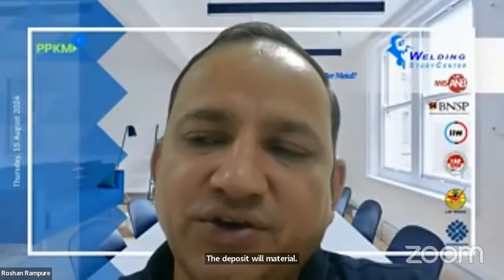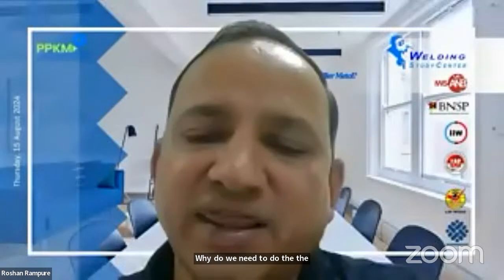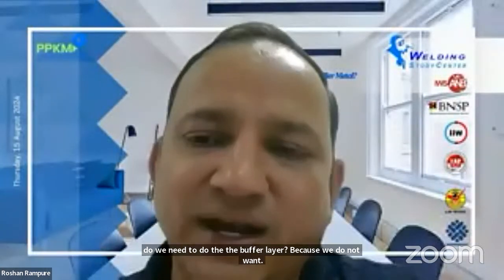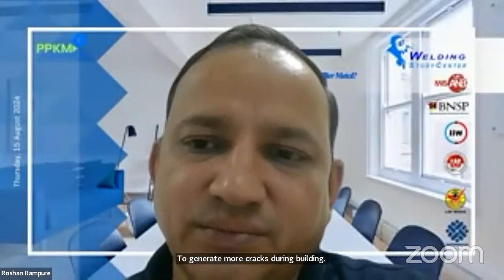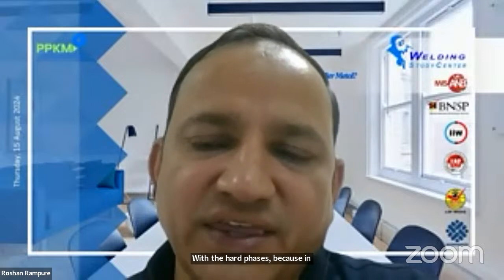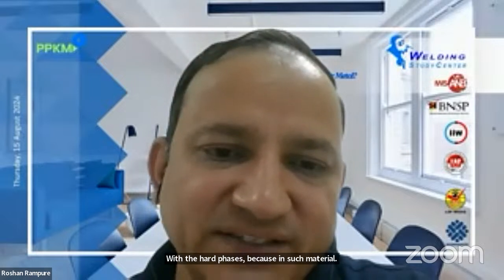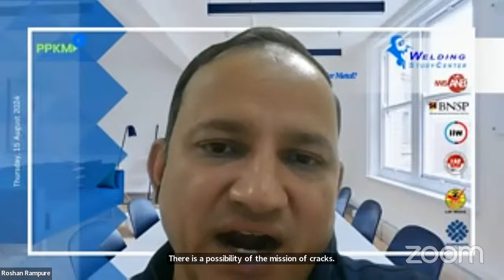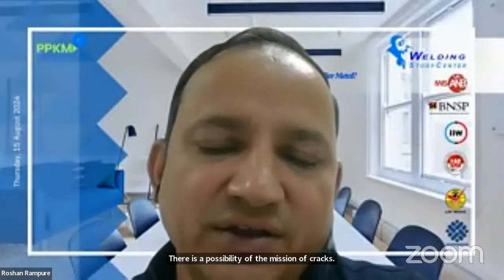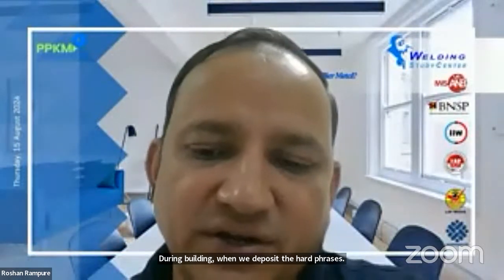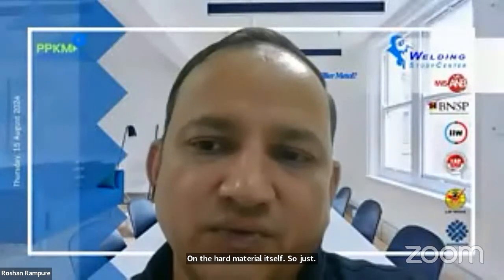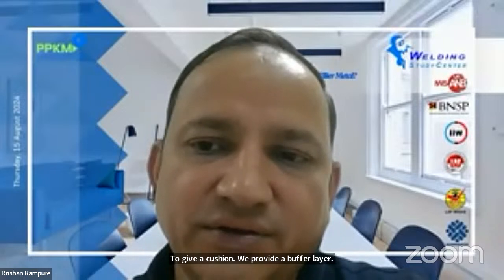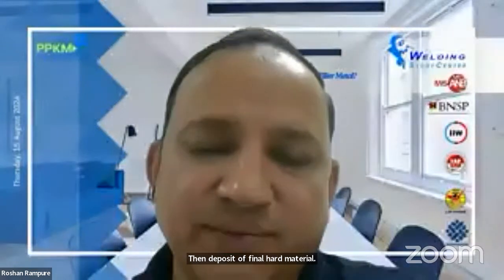Why do we need to do the buffer layer? Because we do not want to generate more cracks during welding with the hard phases. In such material there is a possibility of cracks forming when we deposit the hard deposit on the hard material itself. So to give a cushion, we provide a buffer layer, then deposit a final hard material. That is the generally recommended procedure.